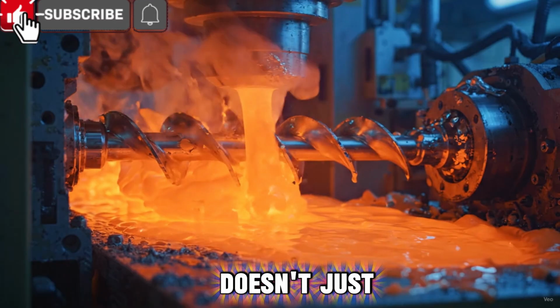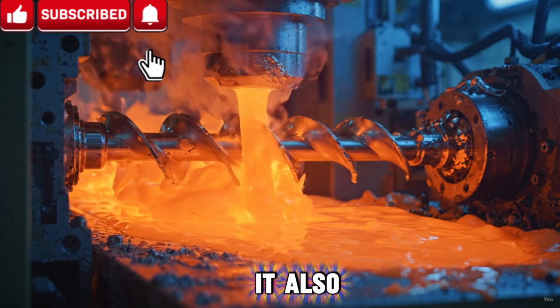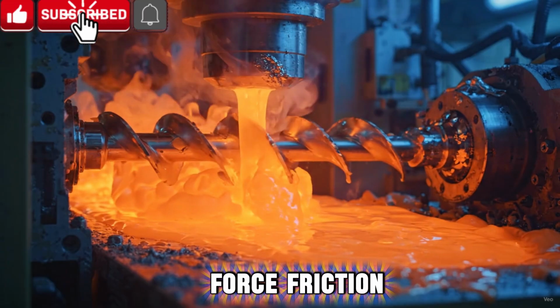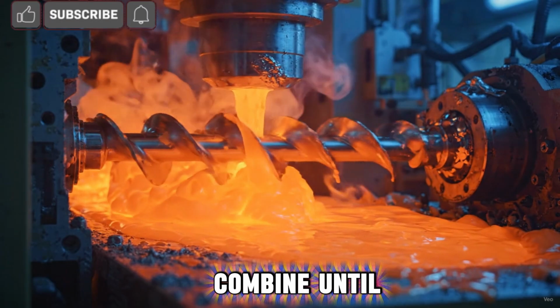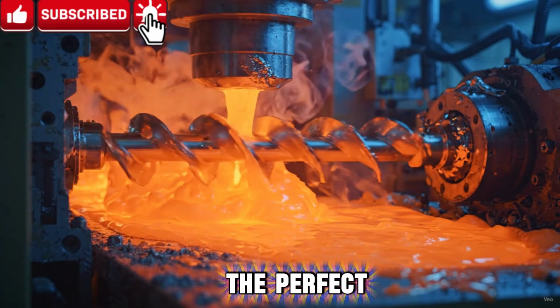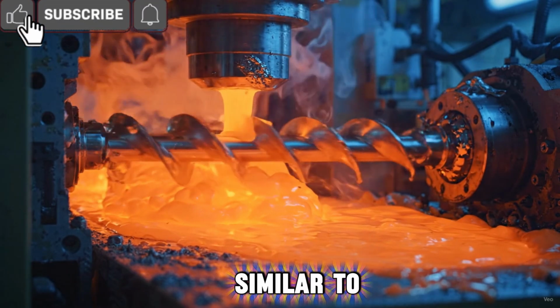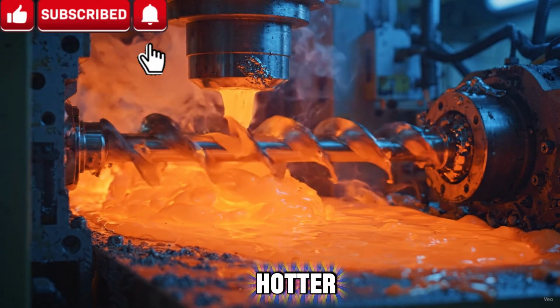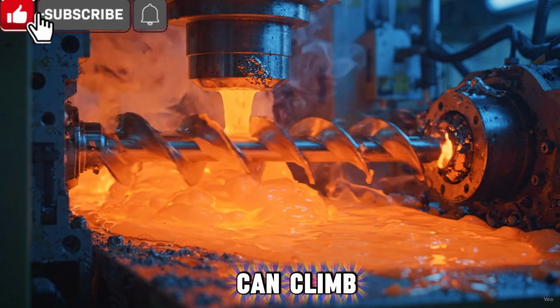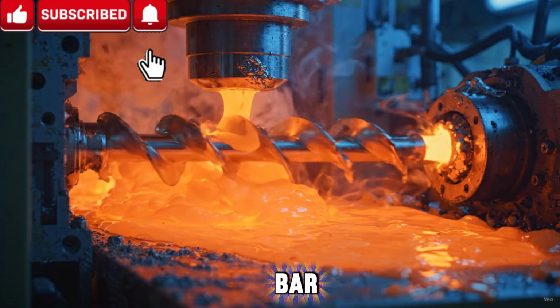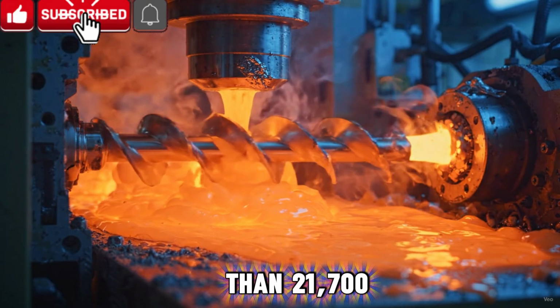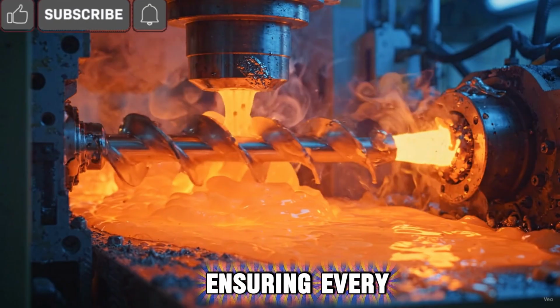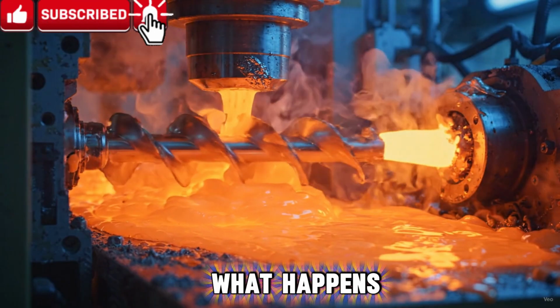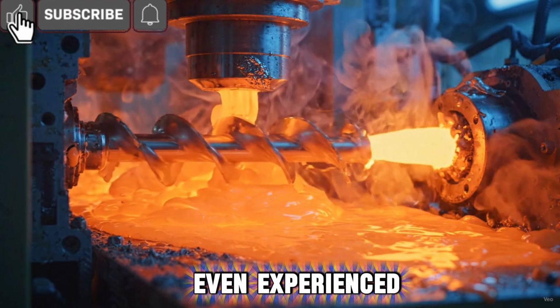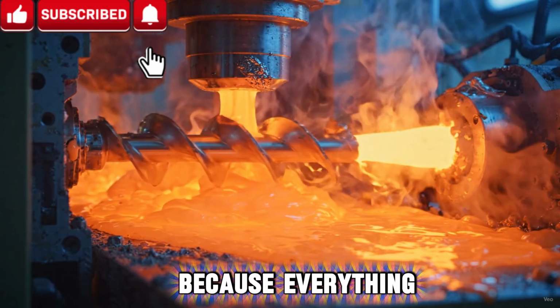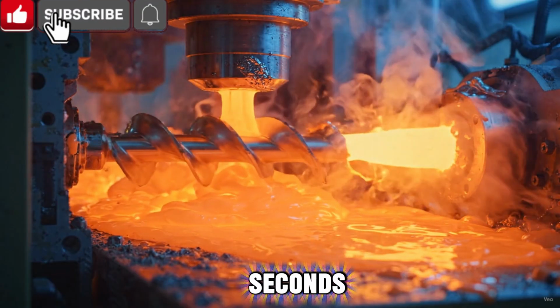The screw doesn't just melt the plastic, it also mixes it with incredible force. Friction, compression, and heat combine until the molten polymer reaches the perfect consistency, similar to thick honey, but hundreds of degrees hotter. Pressure inside the barrel can climb beyond 1,500 bar, or more than 21,700 psi, ensuring every air pocket disappears. What happens next surprised even experienced engineers, because everything must occur in just a few seconds.